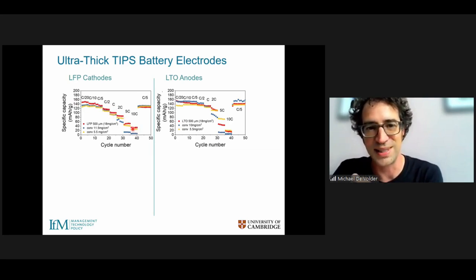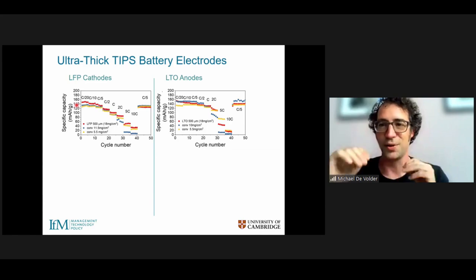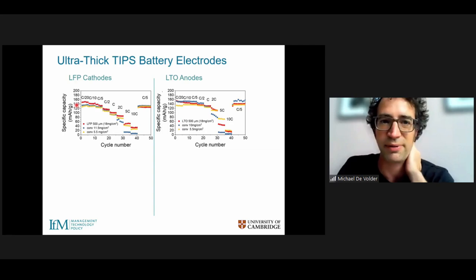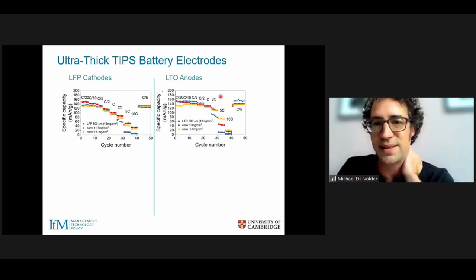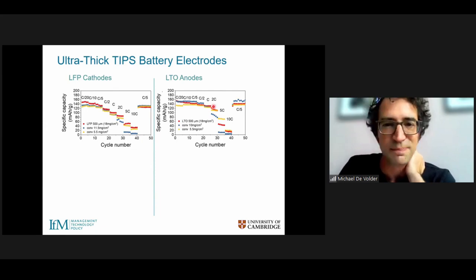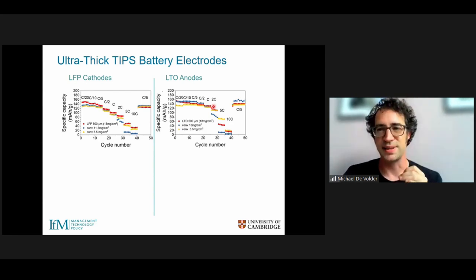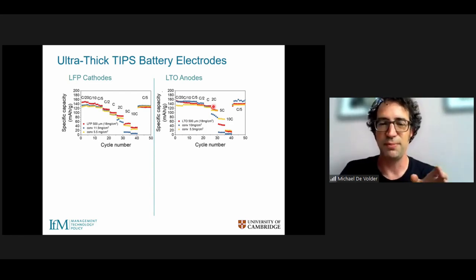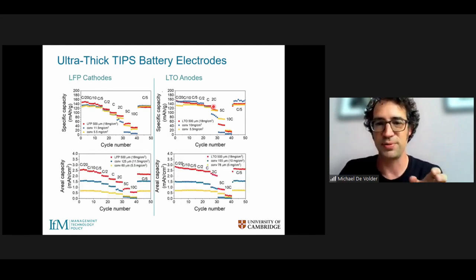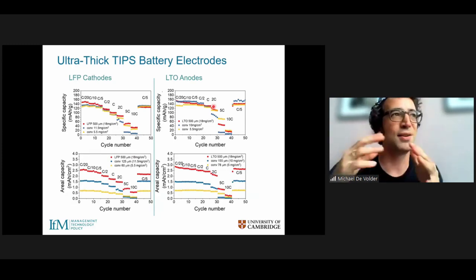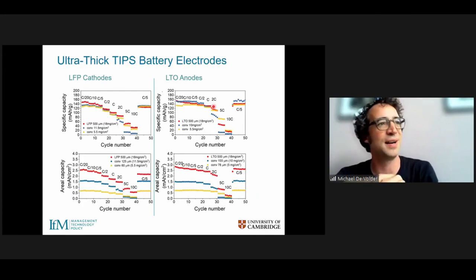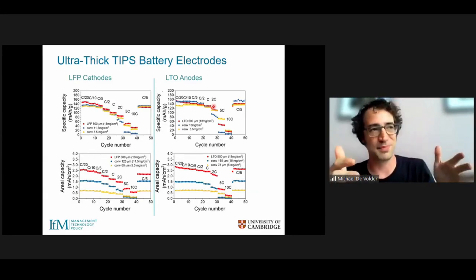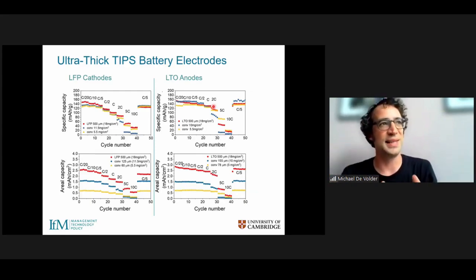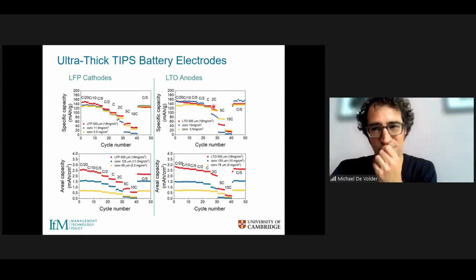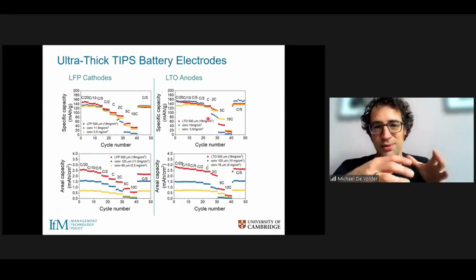I don't want to go too much into these details, but it just shows that our very thick coated electrode performs as expected. And we've done the same experiments for both cathodes on the left-hand side and anodes on the right-hand side. Now, where this becomes interesting is when we start looking at how much energy we can store per area of battery electrode. So if you think back to the little analogy I made in the beginning, if you have very big houses, you can't store many lithium ions per area, but if you start building apartment blocks, you can store much more lithium ions per area, right? And so that's what we are doing here.